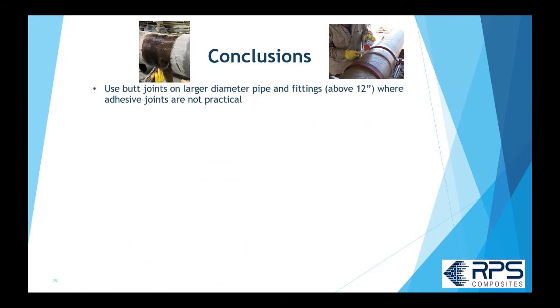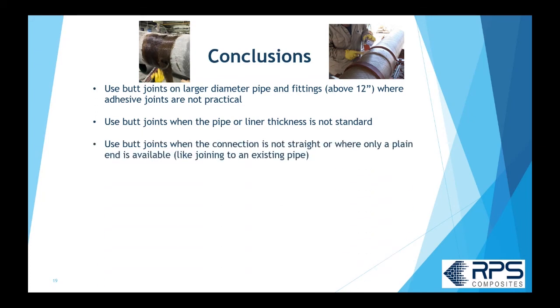So in conclusion, you are going to have butt joints if you have any large diameter pipe above 12 inch where adhesive joints are just not practical. So if you have any larger pipe, you're going to see butt wrap joints in the system. You're going to use butt joints likely if it's not a standard liner thickness, because most manufacturers' adhesive joints are only made for specific thicknesses of piping. You're going to use butt joints if it's not a straight connection. So if you have a miter or something like that, or you're joining to an existing piece of pipe where I don't have a bell, there I'm going to have to use a butt joint.